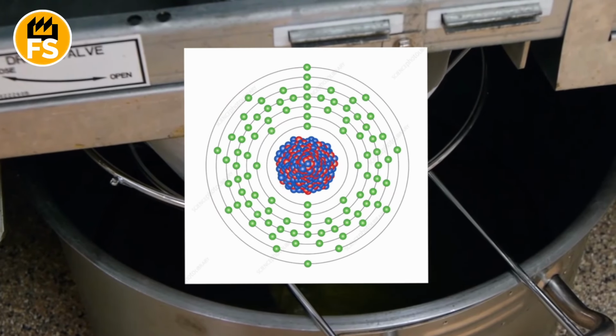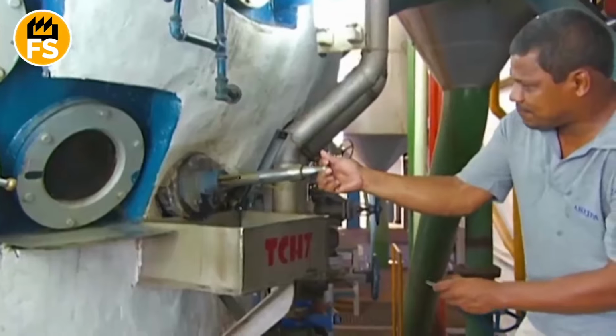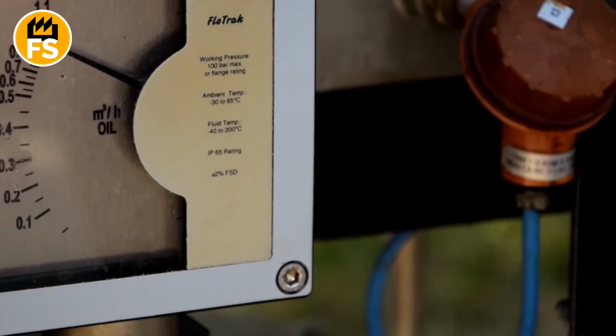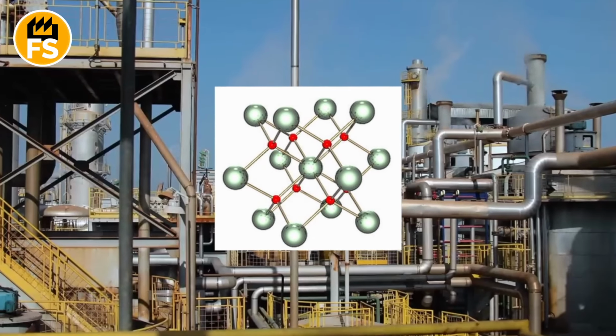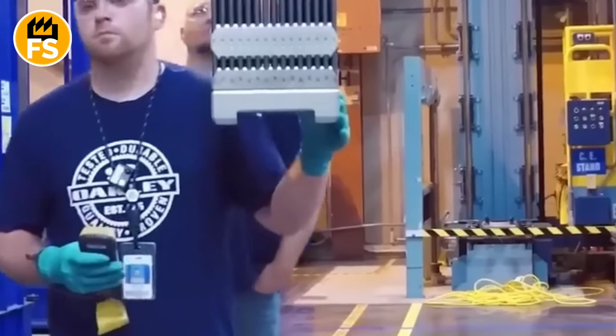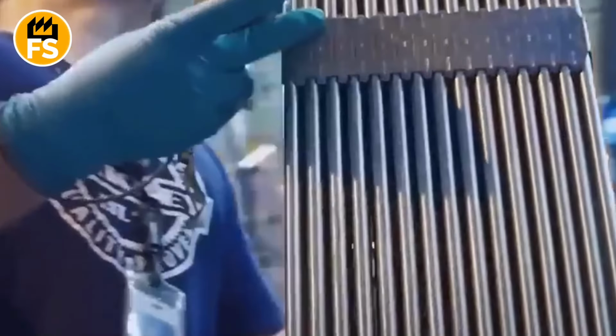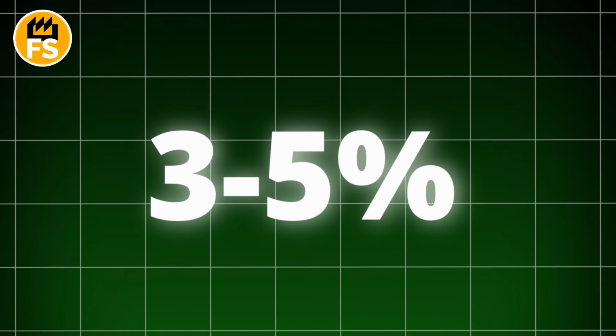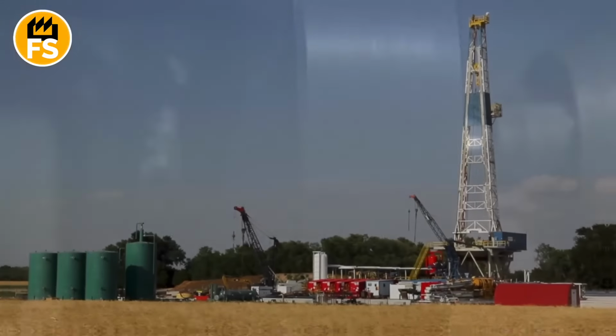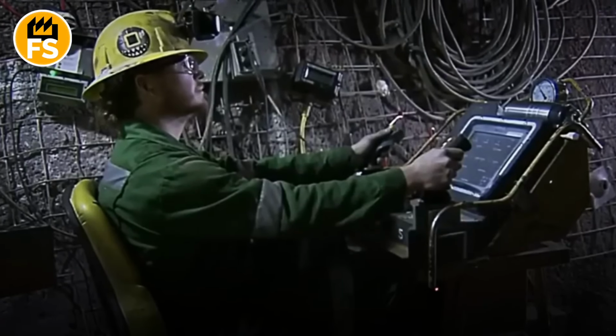The heavier gas molecules with uranium-238, under the action of centrifugal force, are pressed against the walls of the centrifuge, and the very slightly lighter molecules with uranium-235 remain closer to the center. This is a microscopic difference, but it is enough. Special tubes take the gas from the center, which now contains a little more uranium-235, and send it to the next centrifuge in the cascade. And the depleted gas from the walls is diverted to the side. To achieve the required concentration of 3 or 5%, the gas must pass through thousands of such centrifuges. This is an incredibly long and energy-intensive process.